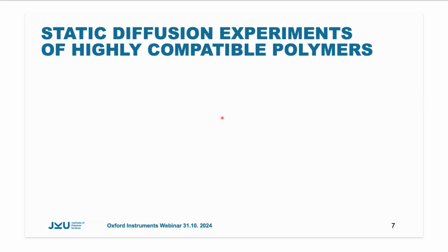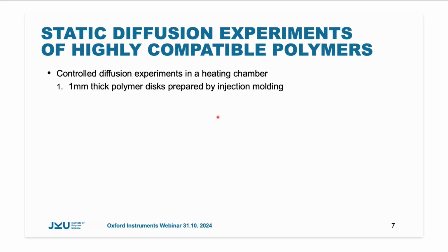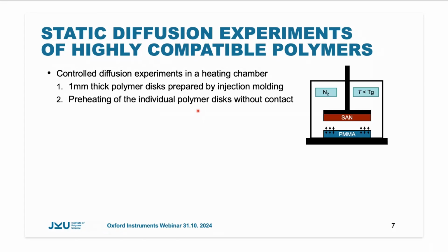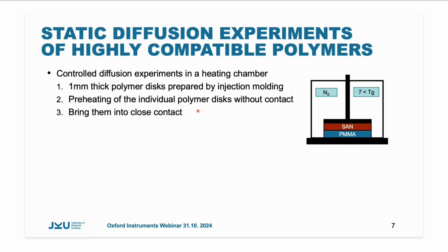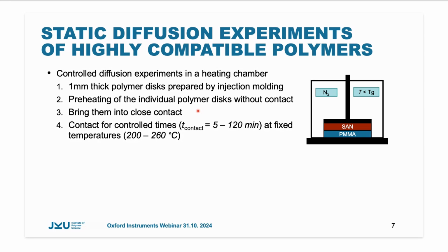Therefore, we perform static diffusion experiments using highly compatible polymers. Our experiments are performed under controlled diffusion conditions in a heating chamber where we mount 1 millimeter thick discs prepared by injection molding. In a nitrogen atmosphere, we preheat the individual polymer discs without bringing them in contact until they get the desired temperature. Then we bring them into close contact for a given time. Contact times are chosen between 5 and 120 minutes at a fixed temperature of about 200 to 260 degrees C. These seem to be very high temperatures, but these are the temperatures which are relevant for co-extrusion experiments.